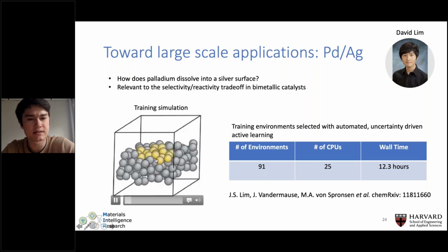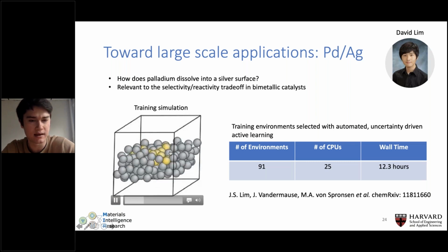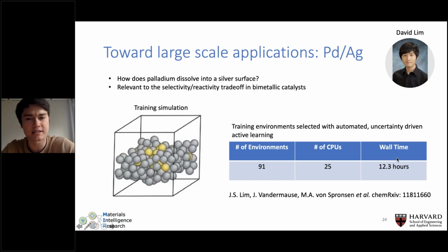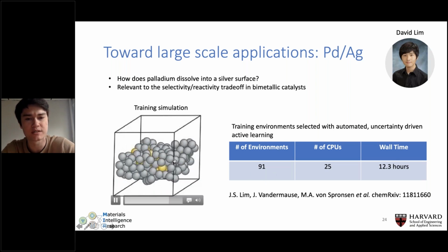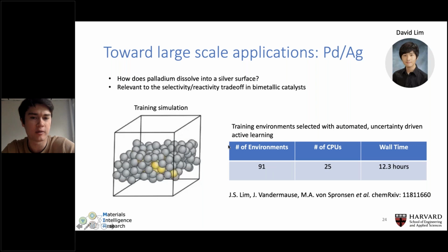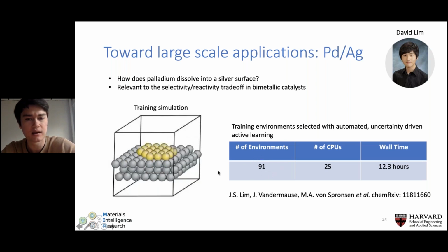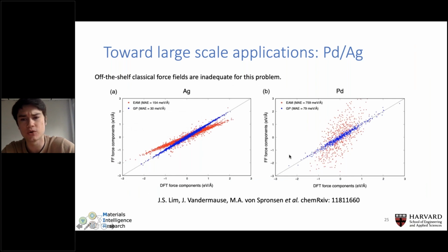So here what we're doing is taking an AIMD training simulation and then performing active learning on it. So we go frame by frame through the simulation and we select the environments that give the highest uncertainties in the GP. Okay, so in the end, for this system, it's a surprisingly modest amount of data that we need to converge the model. And then we can take it and compare it to off-the-shelf force fields. So you can see here, EAM doesn't do the best job of modeling surfaces for this material, whereas we're training directly on ab initio data, and so we get pretty good agreement with DFT.